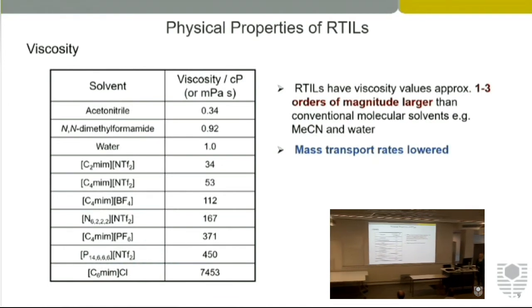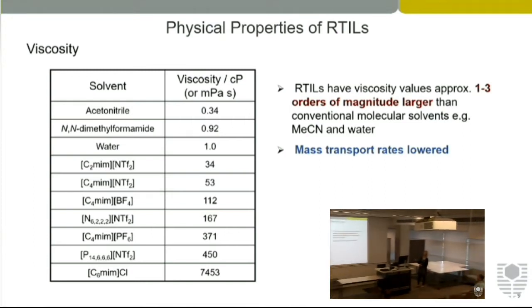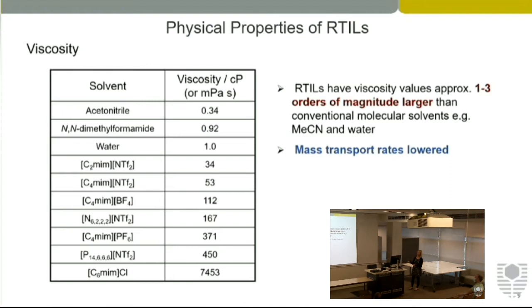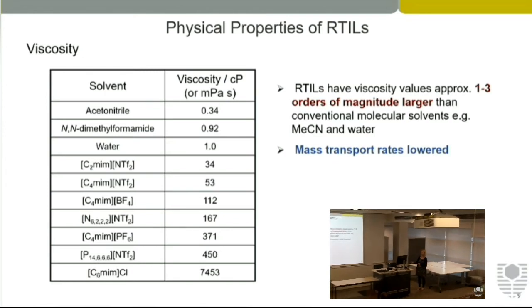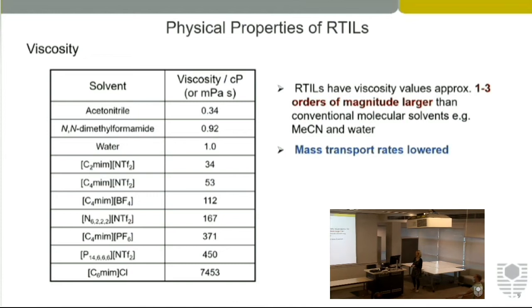So if we take a look at some numbers of some of the physical properties, first of all, viscosity. If you take the viscosity of water as 1, some of the other organic solvents have a slightly lower viscosity. But you can see that different ionic liquids, as you change the chemical structure, are about 1 to 3 orders of magnitude more viscous than traditional solvents. And so when you get to about here, you're looking at more honey type viscosity.